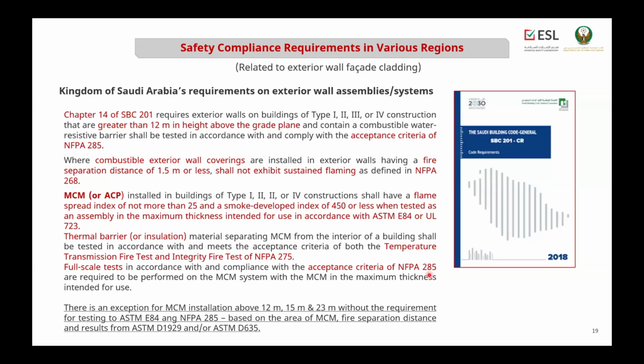They also have separate requirements for specific cladding materials like MCM or ACP. For Type 1 to Type 4 construction, the ACP shall have a flame spread of not more than 25 and smoke development of 450 or less when tested to ASTM E84 or UL 723. The thermal barrier or insulation materials should also pass the test to NFPA 275. They also require full-scale testing for the whole assembly using the MCM system or MCM cladding material based on NFPA 285 testing.